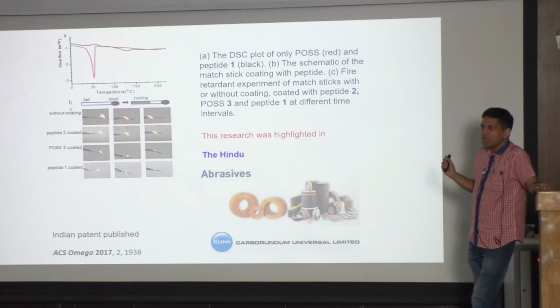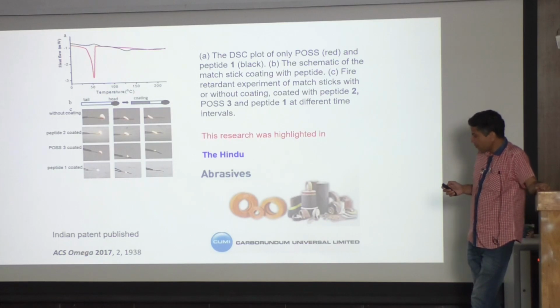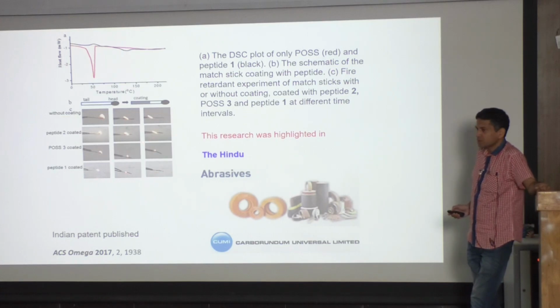I had a little information that polyoxysiloxane can prevent fire. And when we developed this, we took a match stick. We coated half of the match stick with our compound, and without coating, the match stick is completely burning. With peptide only, the flame reaches the match stick and it again burns completely. With only polyoxysiloxane, the flame is reduced, but still the match stick is burned. But with our hybrid compound, it stops at the point of coating. So we can take care of fire now with this compound.